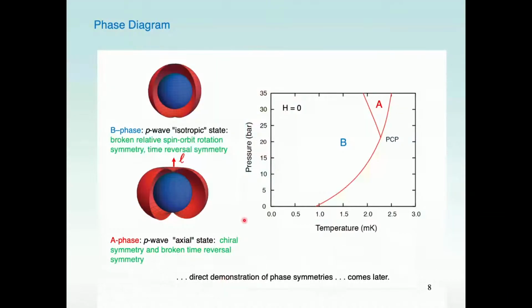So coming back then to the phase diagram, A and B phases, I want to emphasize, as Professor Kono has pointed out, the symmetry of these 2 phases. There are characteristic symmetries, and it's important to have a scheme experimentally to make demonstrations of those symmetries. So the A phase has been discussed by Professor Kono, and in work that they have done at RIKEN, they show that the characteristic symmetry, which is broken time reversal symmetry and chiral symmetry, is manifest. And I'm going to come to that in a minute or so.